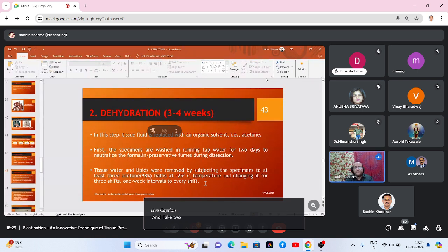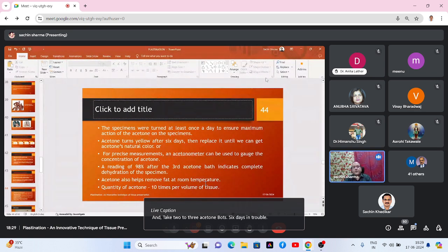We take 2 to 3 acetone baths at 6 days interval. The specimens are turned at least once a day to ensure maximum action of acetone on the specimen. Acetone turns yellow after 6 days, then replace it until we get the natural color of acetone, or we can use an acetonometer to measure the concentration of acetone. If we get 98% concentration after the third acetone bath, it indicates that our dehydration step has been completed. Now the specimen is completely liquid free and fat free.